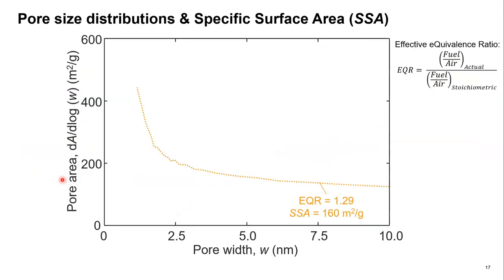So thanks to these high concentrations, we were able to do nitrogen adsorption and obtain the pore size distributions and the specific surface area. So on the x-axis, we have the width of the pores, and on the y-axis, the pore area. So for the leanest equivalence ratio of 1.29, we had a specific surface area of about 160 meters squared per gram. The pore size distributions started off quite small at the large pore widths, and as we go to small pore widths, this begins to increase.